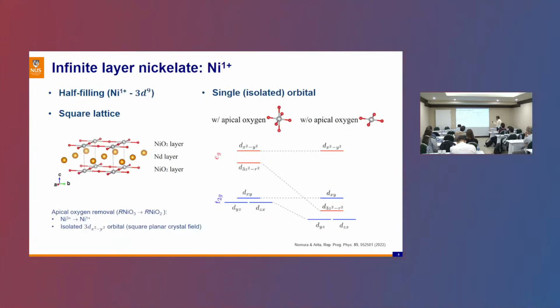So by removing the apical oxygens, you will get these planar structures, right? And these planar structures, through the crystal field, will lead to the isolation of the z orbitals of the 3d, leaving the x² minus y² orbital high in energy and isolated. So basically now you can fulfill all the ingredients that this copper oxide has, okay?